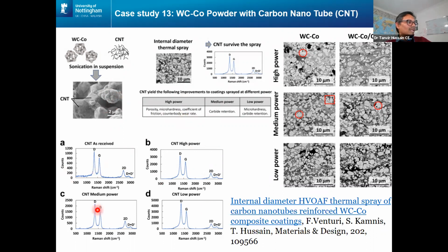What we're looking at is Raman spectroscopy. By looking at the D, G and 2D peaks, we can figure out the level of CNT retention within the suspension, within the powder, within the coating, and after the wear testing. It's a published piece of work in Materials and Design. You can go and read it.